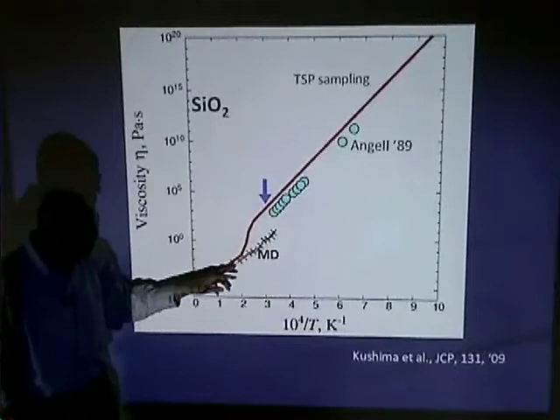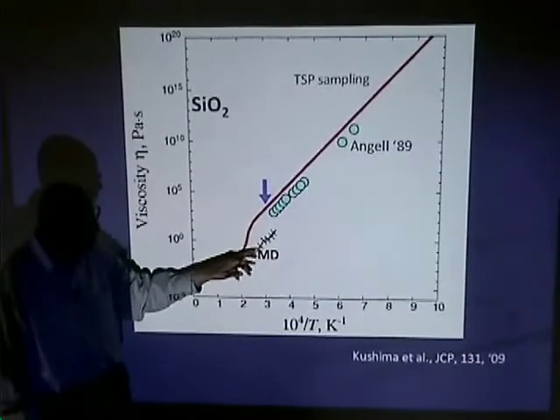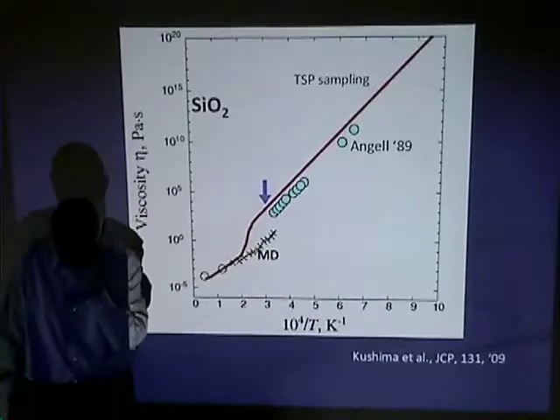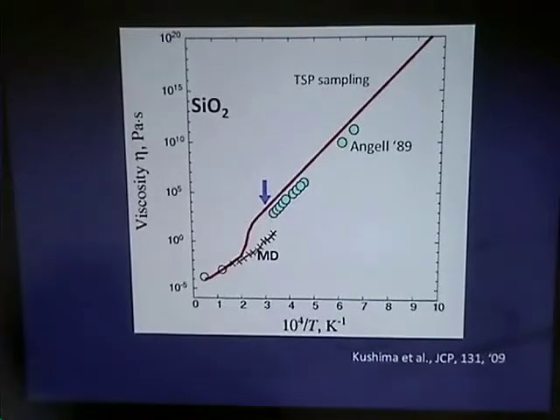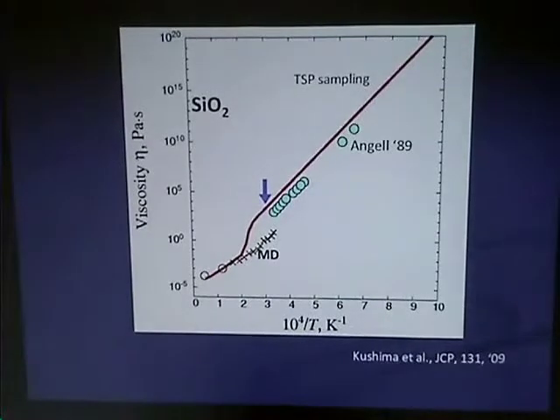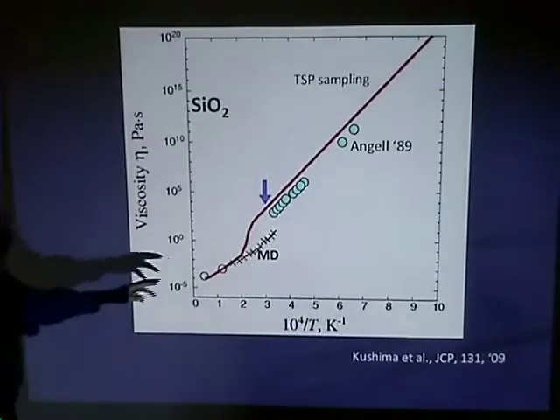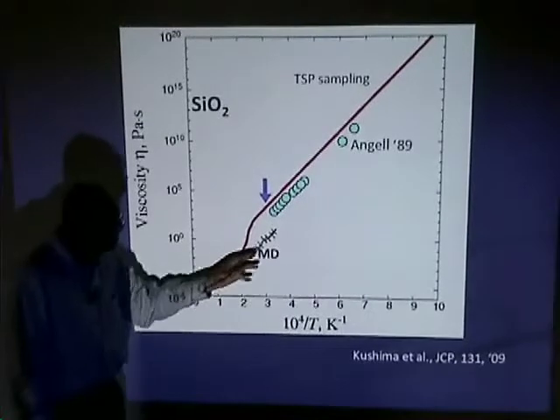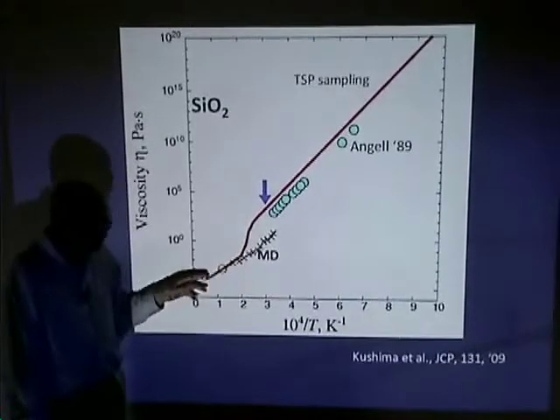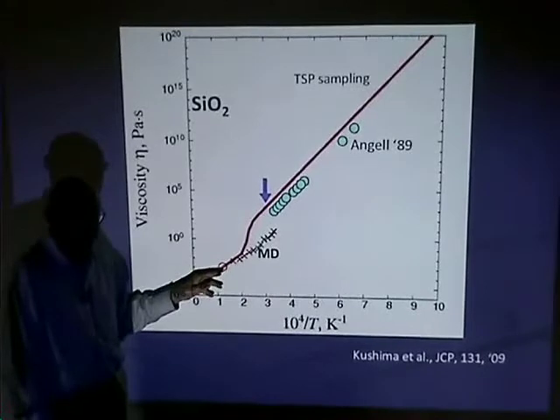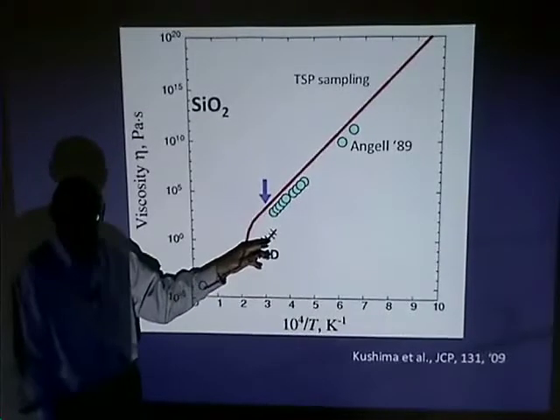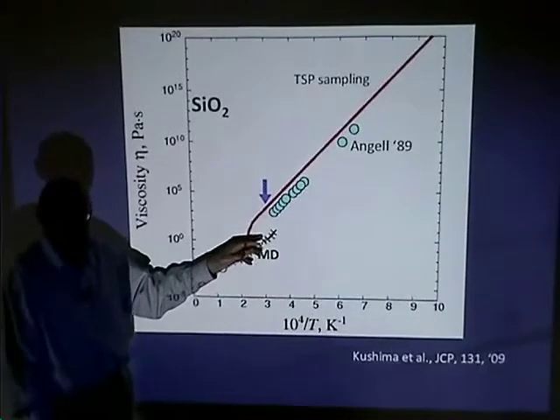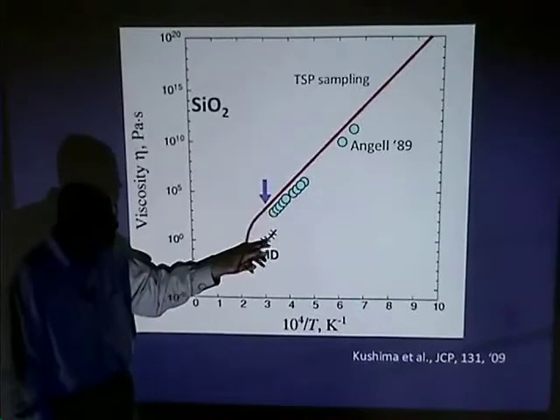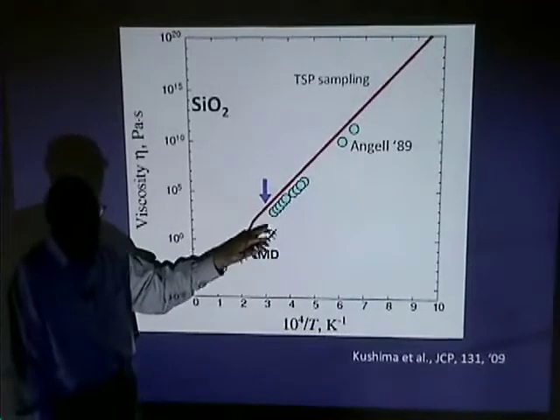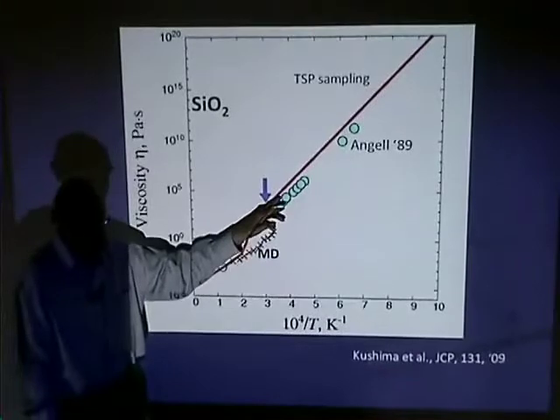And here's some MD result. These are heroic calculations by Horbach and Kob, around the turn of the century, around 2000. And so while we believe this, these two points are our own MD simulation. Excuse me? Different potential. These two calculations use better potentials than ours.